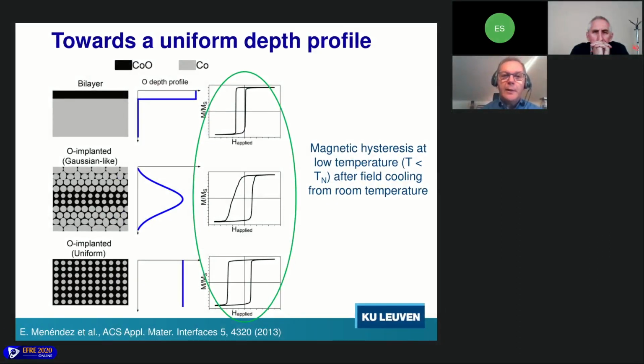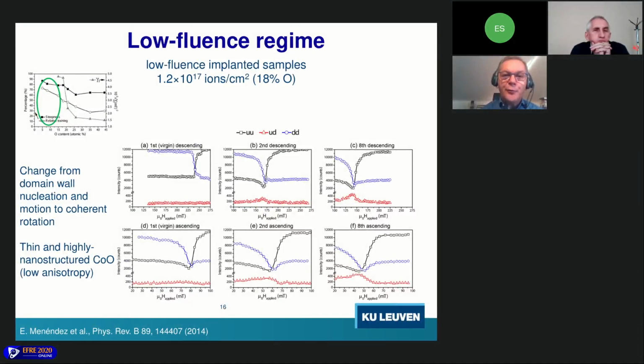Now, finally, and I move to the end of the talk, we have done one more thing. So with our initial implantations, we have a Gaussian-like distribution of oxygen into the layer. In a next step, we have then done implantations at different energies so that you get to a more uniform profile of oxygen throughout the entire layer. And then we have compared that to what we had before. And so, again, we have done a more detailed study of the magnetic properties as a function of the fluence.